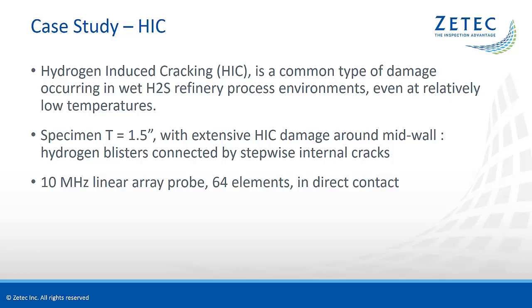The considered specimen is about 1.5-inch thick and has strong hydrogen damage around mid-wall — the typical blisters connected by stepwise internal cracks. A 10 MHz linear array probe with 64 elements was used for the examination, in direct contact with the specimen.